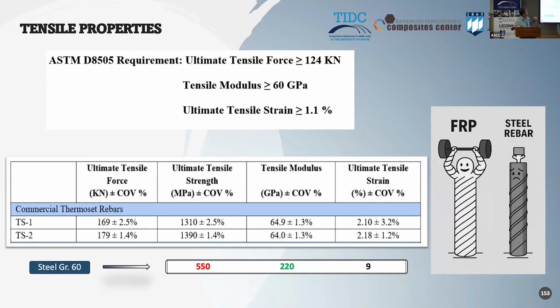And we take a look and see what happens with steel. If we had an idea about how steel works, of course, the tensile strength of steel is not as high. About a third of what we would obtain with, this is for a steel grade 60, okay? And this is going beyond yielding, if what we obtain for the composite rebar. The steel, what it has is higher modulus, right? But these rebars are hitting the requirement of the standard. Again, this is the requirement that ACI and AASHTO call in when they are designing for these rebars. And what we're doing here, again, is verifying that, as well as the ultimate strain. Next.